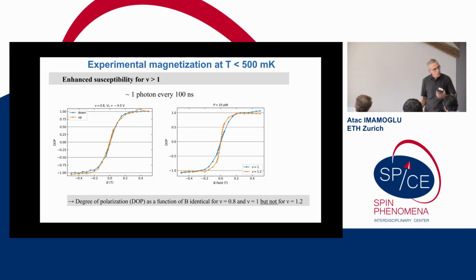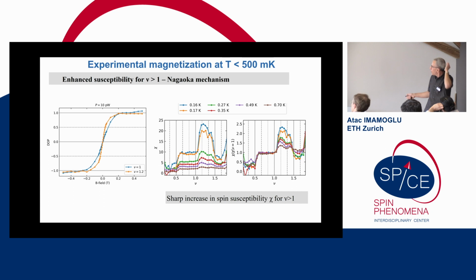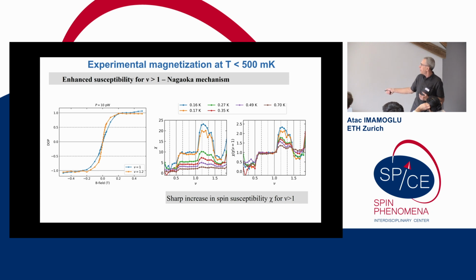Not ferromagnetic order, so we're still above the temperature. So the critical temperature, despite this enhancement, despite being proportional to the hopping, still is below the temperatures we can reach. Okay? And this is now the spin susceptibility as a function of the filling factor. So you see that it's basically flat, nearly paramagnetic on the hole doping side all the way up to nu equals 1. And then there's a sharp increase associated with the Nagaoka ferromagnetic correlations.